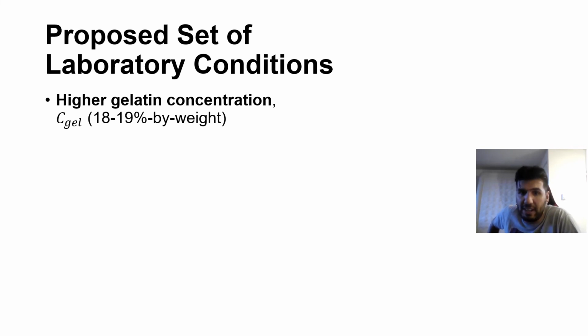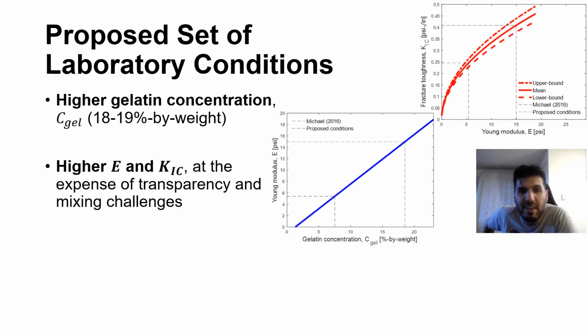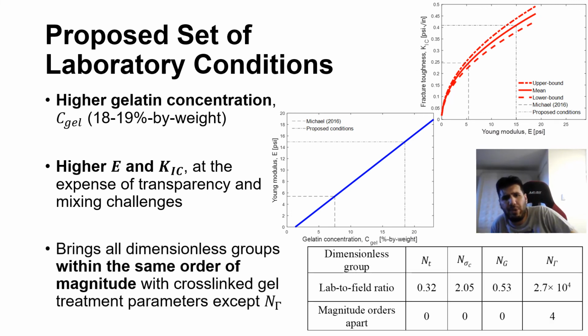I used a higher gelatin concentration of 18 to 19% by weight in my estimations. This will yield a higher Young modulus and critical stress intensity factor, as we see from the correlations of Michael, but there would be added transparency and mixing challenges. I don't believe those would be detrimental, but they'll be quite hard to overcome. And as a result, I was able to get all dimensionless groups within the same order of magnitude when compared to the crosslinked gel fracture treatment, except the dimensionless group for the crack formation energy, which was decreased, but still remains 4 orders of magnitude apart between laboratory scale and field scale.